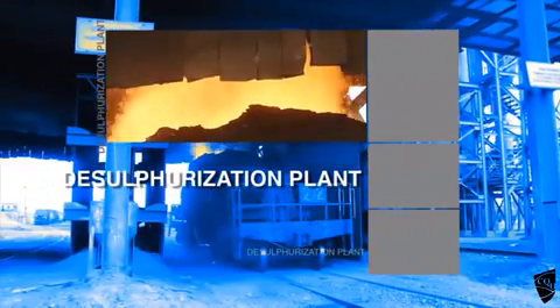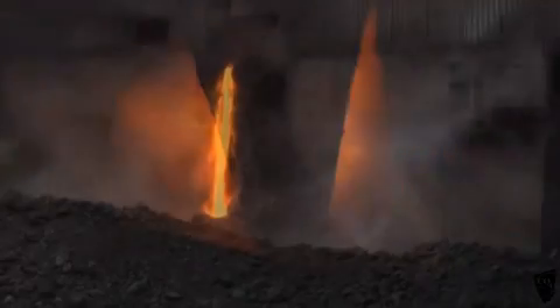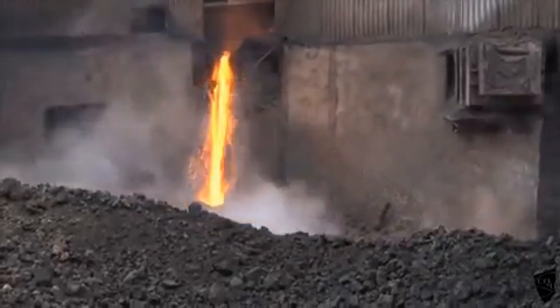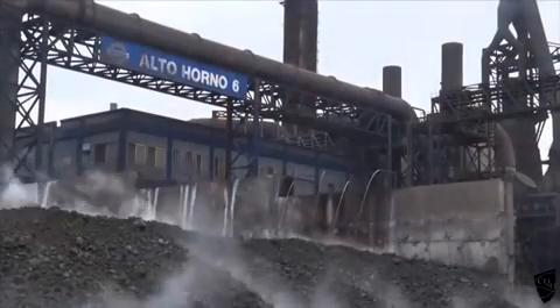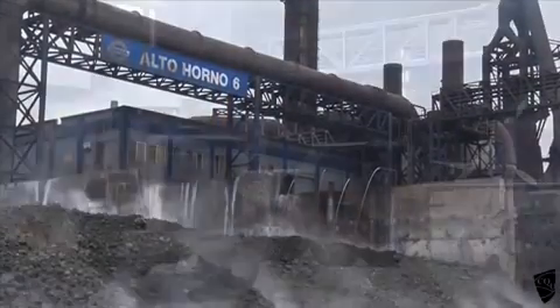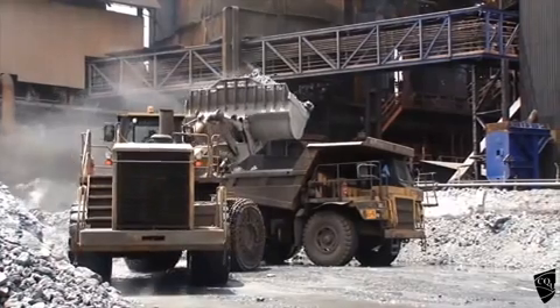In order to eliminate sulfur content, reagents such as calcium carbide and magnesium are applied to the pig iron in the desulfurization plant. The slag generated during the smelting is deposited in a slag pit to be cooled with water. It is later stored or sold as a byproduct.